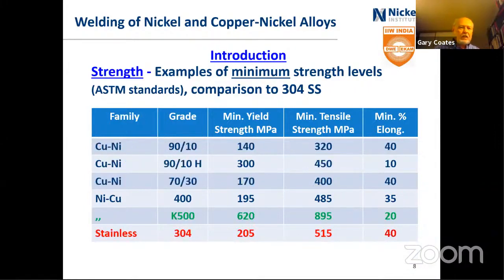When it comes to copper nickel, they are both in the fully annealed condition weaker than a 304 material, and just like the alloy 400, they're even weaker than that. The Monel K500, or the precipitation hardening grade or age hardening grade, is a lot stronger. You can see the yield strength is a lot higher than either the stainless steels or the copper nickel alloys, or the pure nickel copper alloy.